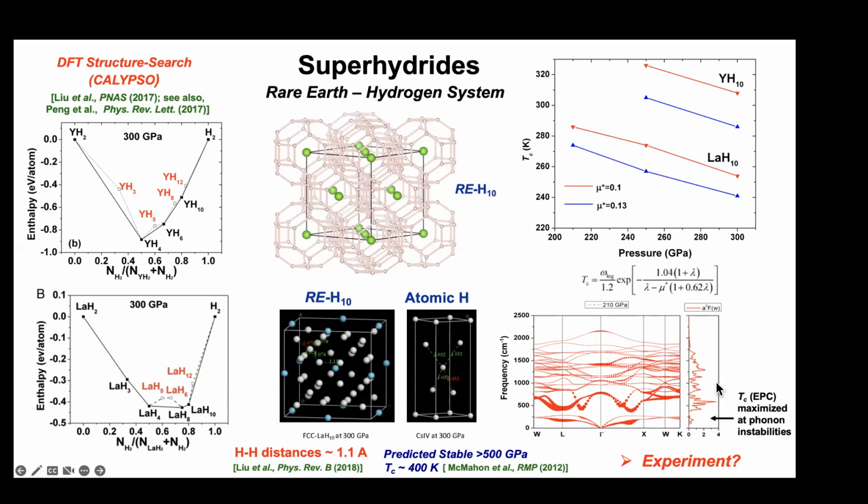An important point of this is that also, in addition to the simple idea that you have very high Debye frequencies or average frequencies and strong electron phonon coupling at high frequencies, at very low frequencies you have strong electron phonon coupling, and the highest TCs emerge as you approach these dynamical instabilities that give the high TC but also limit the stability, at least in these quasi-harmonic calculations, put a bound on the pressure dependence.